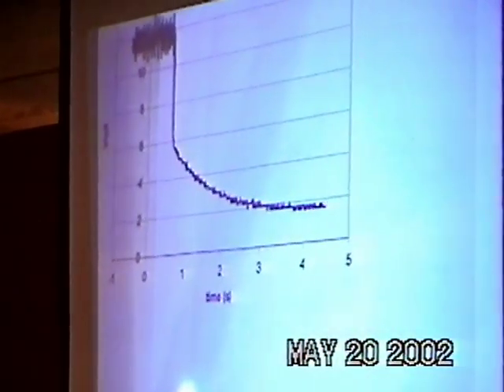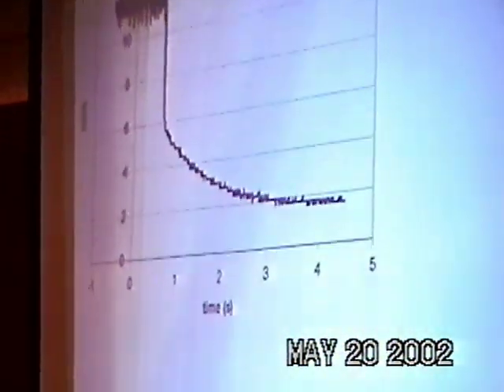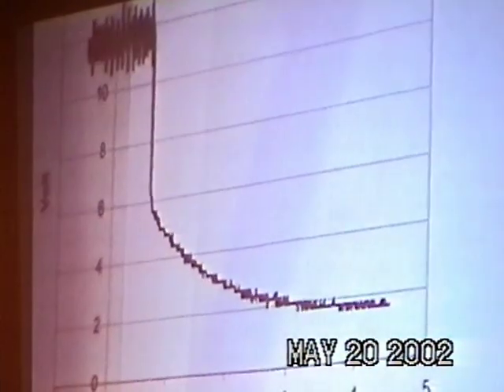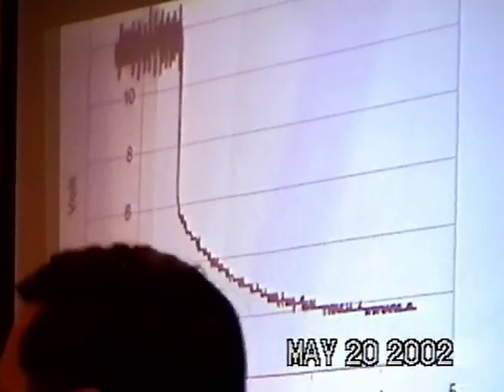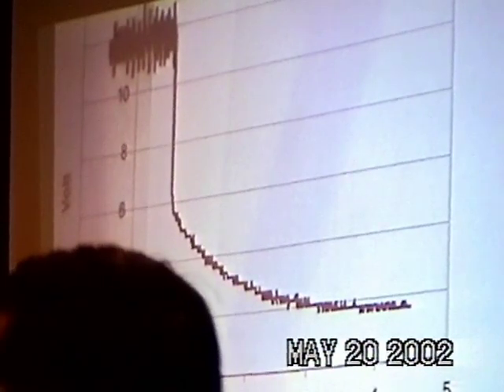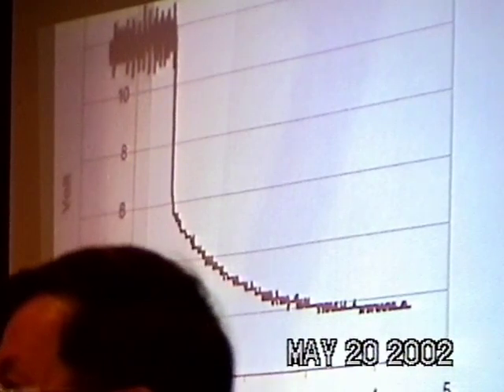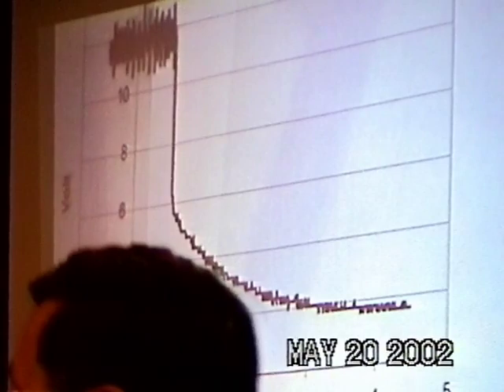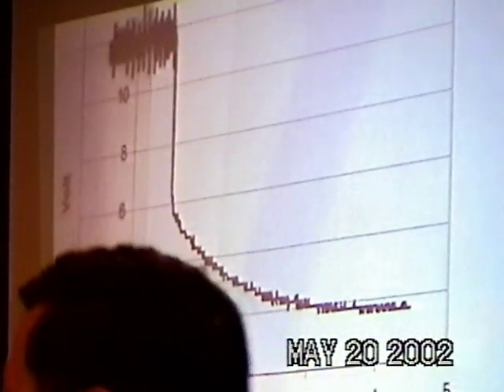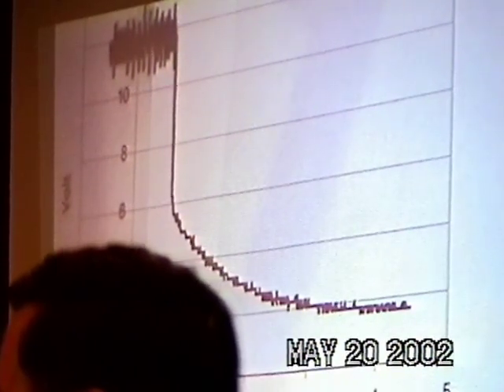We have a graph which shows the falling down of the cell voltage when switching off the current. That ensures, by the way, that we can stop for a very short time the current of the cell for measuring the resistance without losing anything, because you can see that there is a discharge curve whose typical time is more than 1 second, 1.16 seconds, which corresponds, given the cell resistance, to a capacity of about 20 microfarad per square centimeter of the electrode. So we have the theoretical prediction and the experimental check of this one.